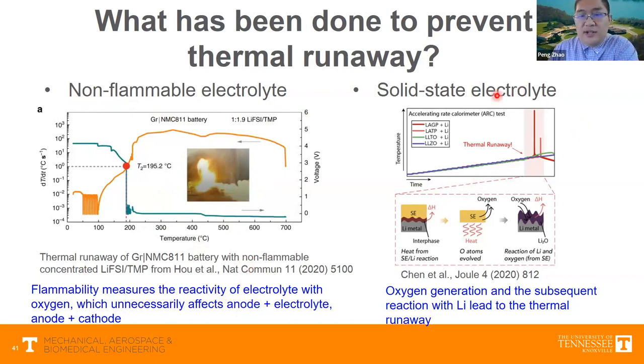And also recently there has been extensive interest in solid state electrolytes, but no matter what material you use, they largely still have thermal runaway. One of the leading mechanisms is that the metal oxide as ion conductor can decompose and release oxygen. And this oxygen will react with the lithium and trigger thermal runaway.